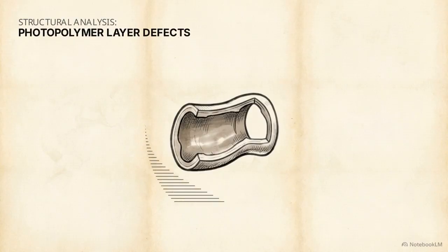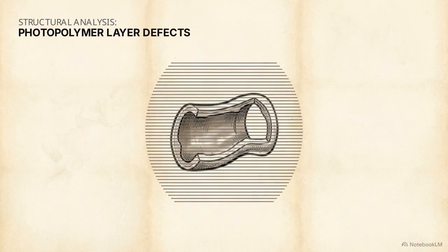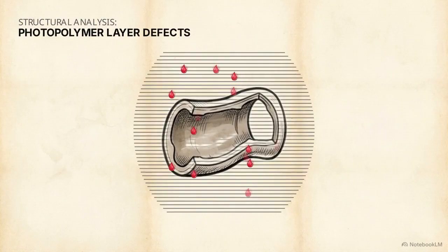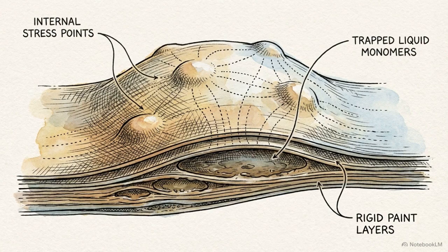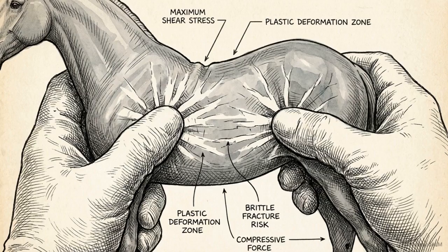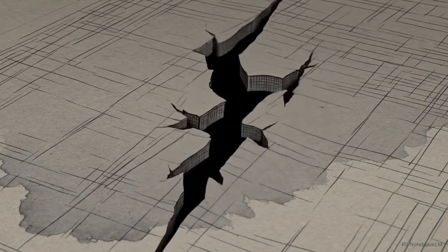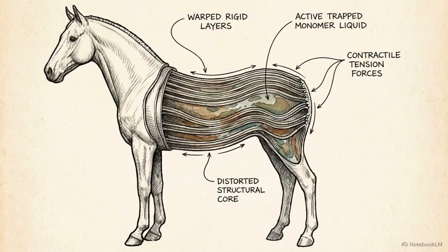The layer-by-layer construction method leaves microscopic seams throughout the entire interior of the horse. During the printing process, small amounts of raw, uncured liquid resin can become permanently trapped inside these microscopic gaps. As the model continues to post-cure over months, internal tension builds around these trapped liquid pockets. This persistent internal stress causes the photopolymer to become increasingly brittle. Eventually, the material can no longer hold the tension, resulting in jagged microcracks splitting through the smooth surface and the paint above it. The internal chemistry of a 3D printed model remains active, shifting and contracting long after printing ends.